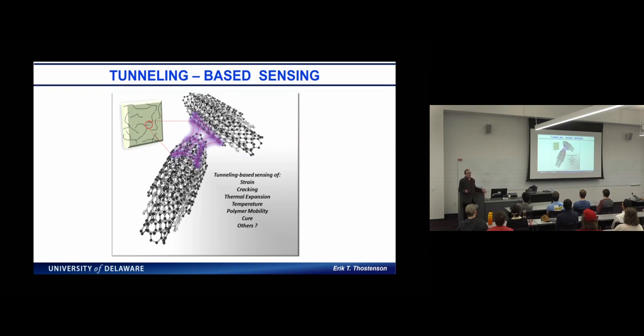And one of the unique things, and what's really enabled a lot of my research over the past 10 years, is that these carbon nanotubes are conducting. If we create networks of carbon nanotubes, we can add just a small amount and make something electrically conductive. But what dominates the conductivity is not the conductivity of the reinforcement. It's actually that contact resistance or quantum tunneling resistance. So a lot of things can happen.